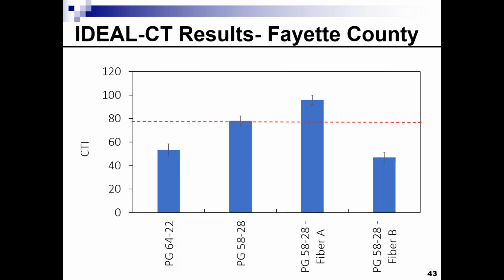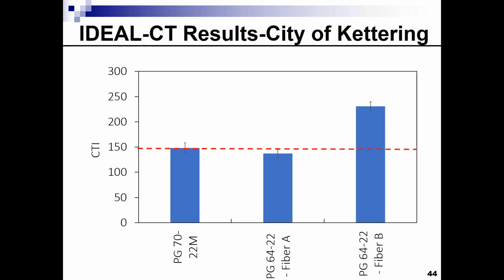If we're looking at Fayette County, what we have noticed is that with the PG58-28, fiber A seems to be improving the CTI and the cracking as compared to the PG58-28. Fiber B actually reduced it, but it was very similar to the 64-22. It might be because of the components, which is a plastic fiber that is being used as a delivery system for that fiber. It might have stiffened the mix and caused that issue.